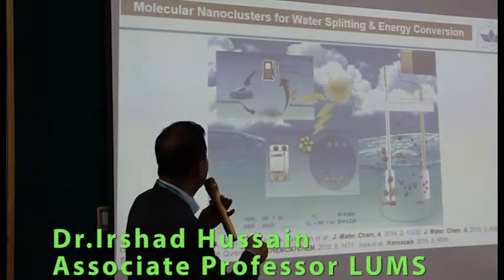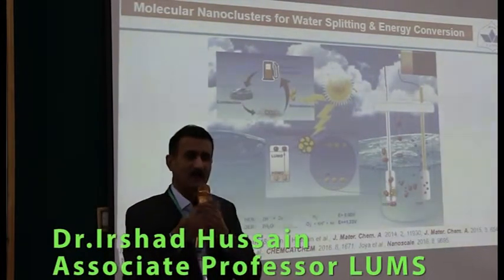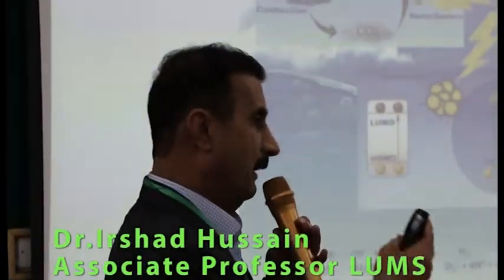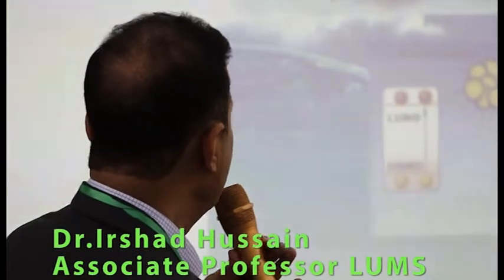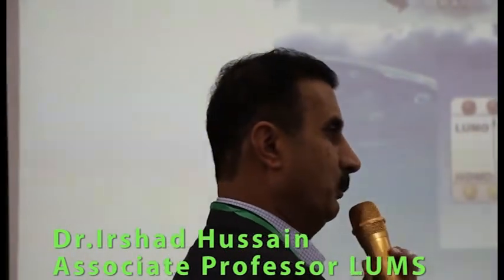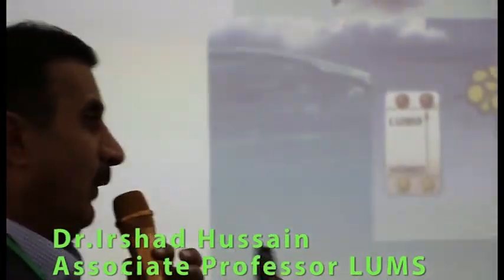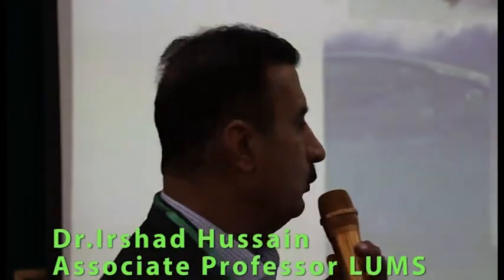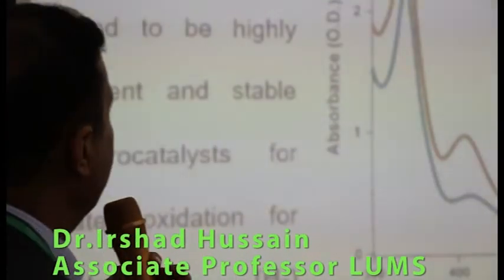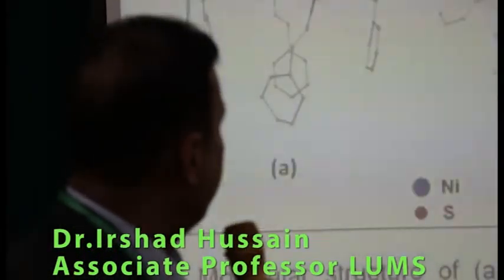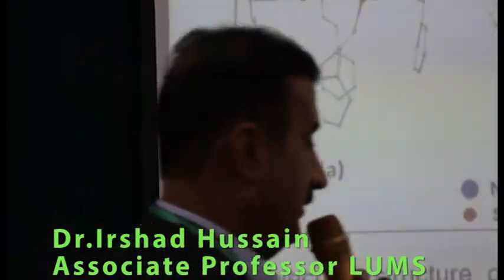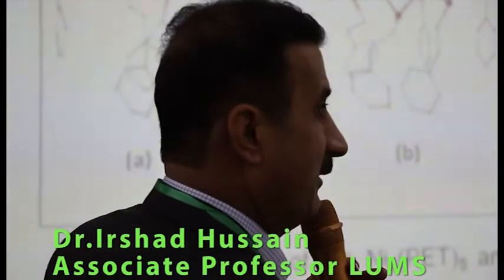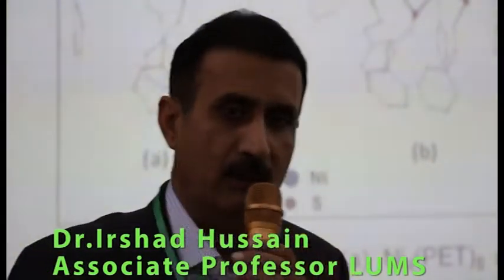So for that purpose, we are working nowadays on nanoparticles of iron oxide, of nickel, of copper, of cobalt, which are really abundant. And then use those to separate water to produce hydrogen. We know in principle water can be separated to produce hydrogen. But the amount of energy that is required to separate water is more than the energy you will produce from it. So you really need to develop catalysts which can reduce the energy that is required to separate water into hydrogen. And for that purpose, we have produced several nickel-based, copper-based nanoclusters and iron oxide nanoclusters, which contain only nickel 4 atoms or nickel 6 atoms, and they are very, very effective for water separating applications.